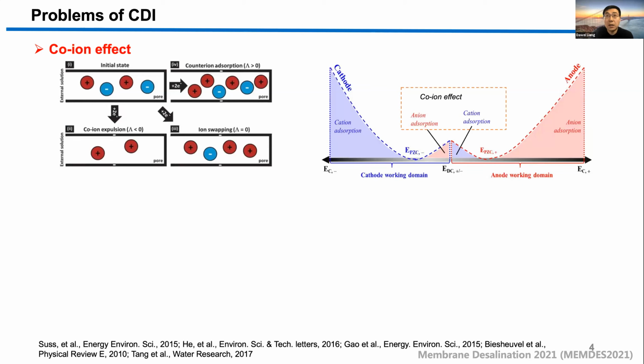One is the co-ion effect. When you charge the electron into the electrode, the ideal condition is that the electrode absorbs the counter ions, like this part. But in fact, on some occasions, it could repel the co-ions into the water as well. And even in some cases, ion swapping occurs.